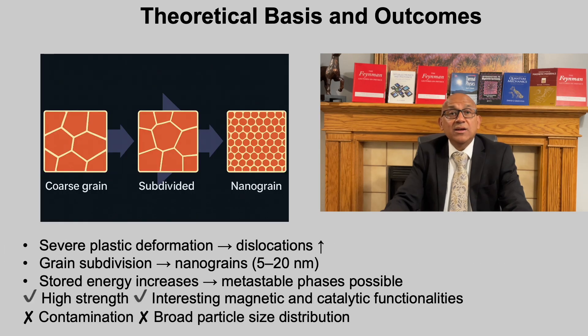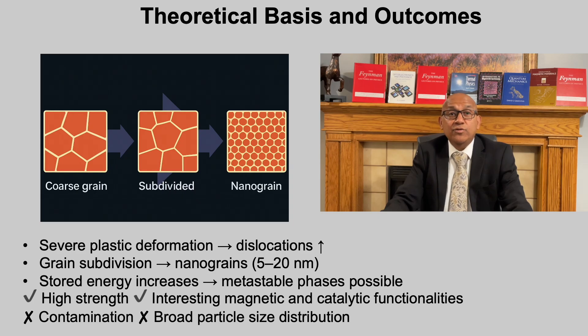At the atomic scale, ball milling induces severe plastic deformation. Dislocation multiplication subdivides grains into nano-sized domains, while stored strain energy may stabilize metastable or amorphous phases. As a result, we can obtain nanocrystalline metals, alloys, ceramics and composite powders exhibiting enhanced mechanical strength, magnetic behavior or catalytic activity. Nevertheless, challenges remain: contamination from the milling media, broad particle size distribution and difficulty in achieving large-scale uniformity. Understanding these trade-offs helps select optimal milling conditions for each material system.